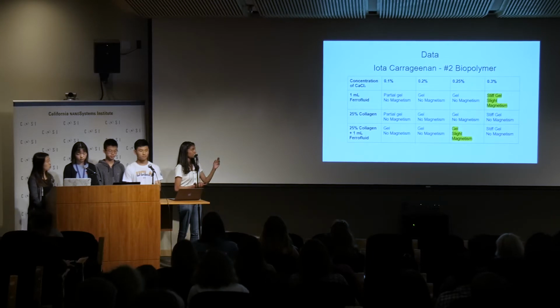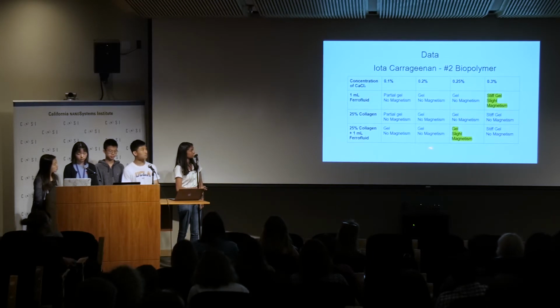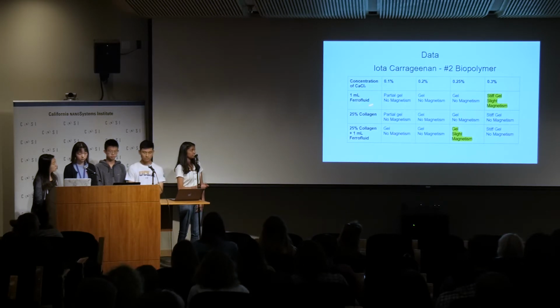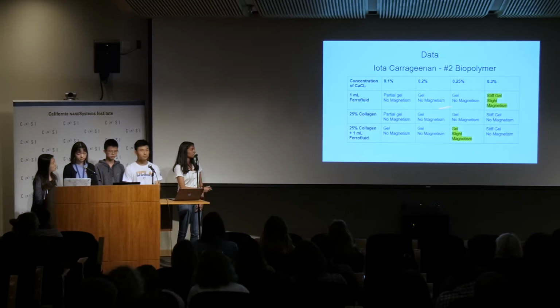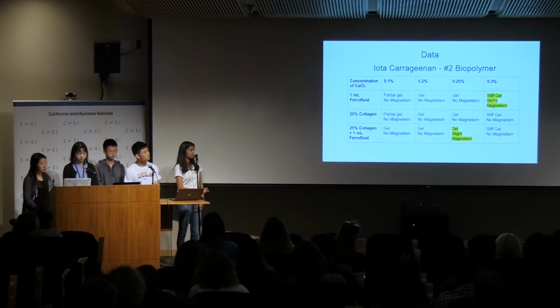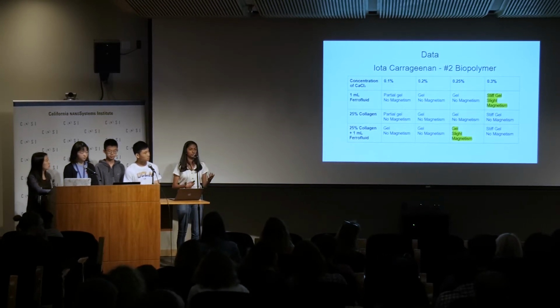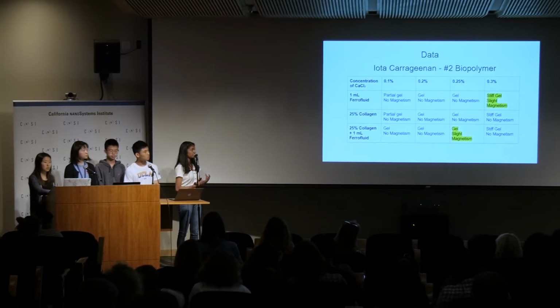So we had 3 variables for the concentrations that we had. So first was just ferrofluid. So we did that for every concentration of CaCl2, and then we just had one with 25% of collagen, and then we had one where we combined both of them. And highlighted, you could see the ones that we found most ideal, which had the balance between the solid and liquid state of matter, and it had slight magnetism.